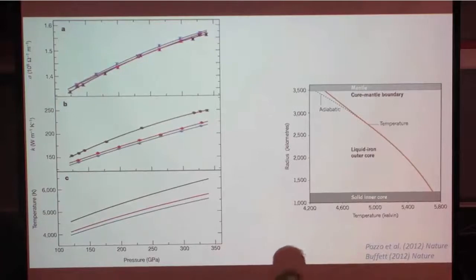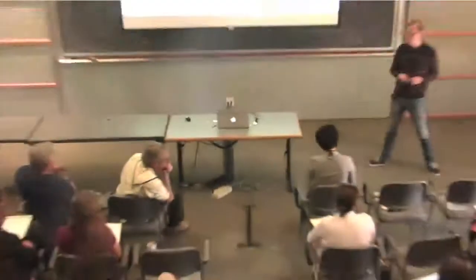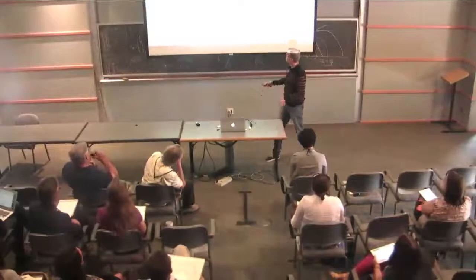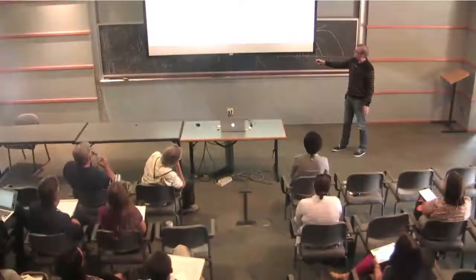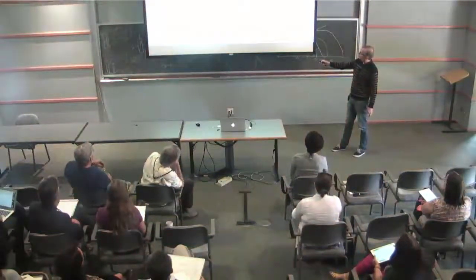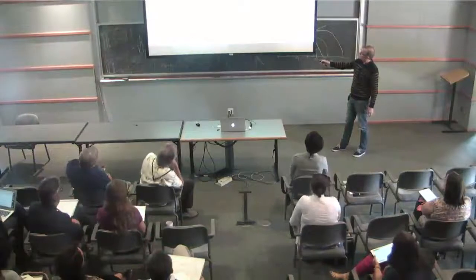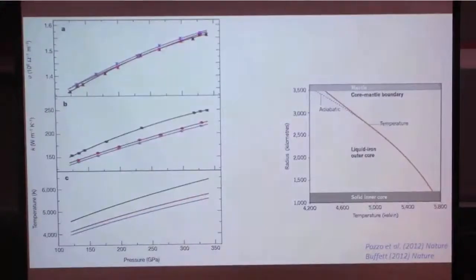Yes? Do you envision any impact from light elements on those thermal conductivity measurements, or is it so small that it's not going to impact? They looked at that, actually. So what these three curves are: black is pure iron, red is for a silicon-oxygen mixture, and blue is for a sulfur-oxygen mixture. So it's still high.